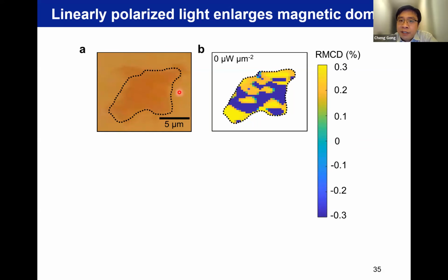We know if you have a 2D FGT here, an itinerant ferromagnet, and you cool it down in darkness, which is usually what people did, at room temperature it's a non-magnetic phase. Cool it down across TC, like this 4-layer sample. TC is about 140 to 150 K. You cool it down, likely you will form these multiple magnetic domains. This is reflectance magnetocircular dichroism. You can understand the different colors as different magnetic domain orientations, spin up and spin down.